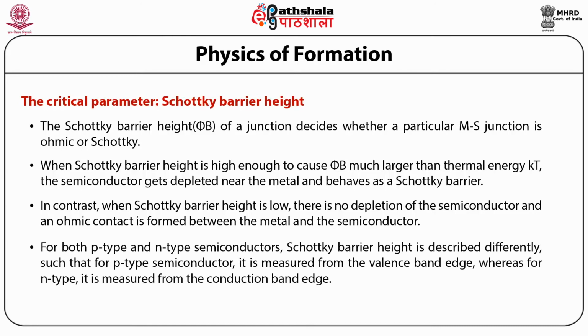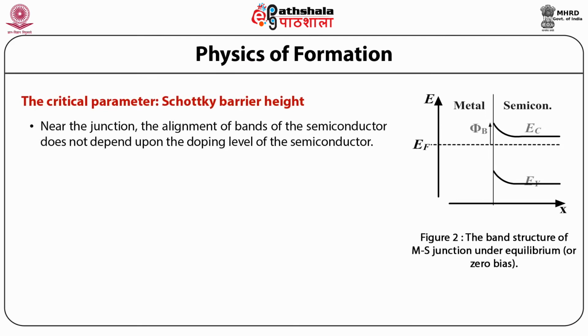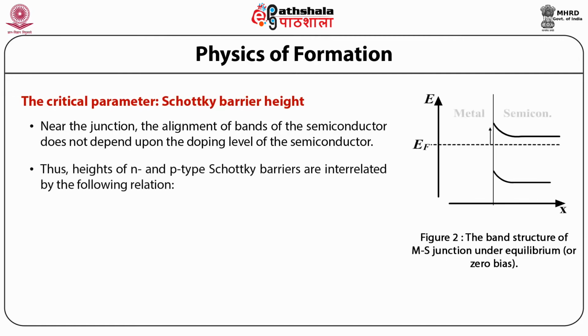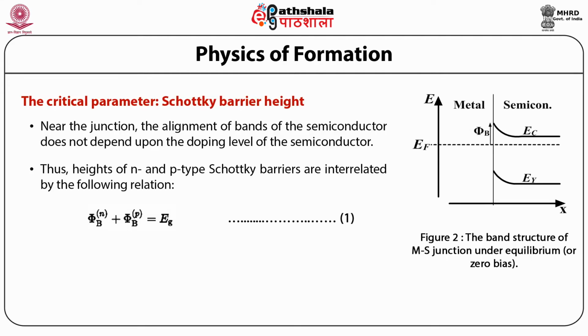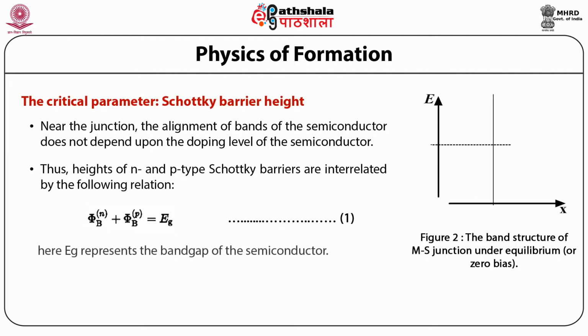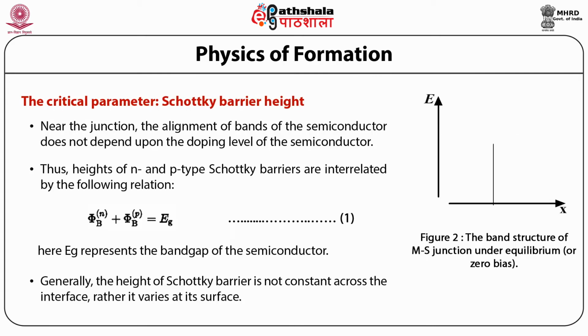For both p-type and n-type semiconductors, the Schottky barrier height is described differently, such that for a p-type semiconductor, it is measured from the valence band edge, whereas for n-type, it is measured from the conduction band edge. Near the junction, the alignment of bands of the semiconductor does not depend on the doping level of the semiconductor. Thus, the heights of n-type and p-type Schottky barriers are interrelated by the following relation. Here, phi b raised to power n plus phi b raised to power p is equal to Eg. This is represented as equation 1. Here, Eg represents the band gap of the semiconductor. Generally, the height of the Schottky barrier is not constant across the interface. Rather, it varies at its surface.